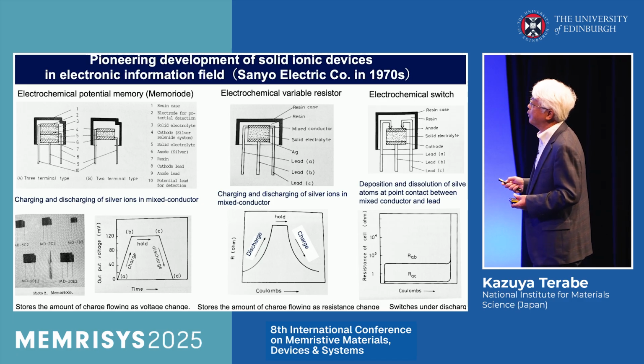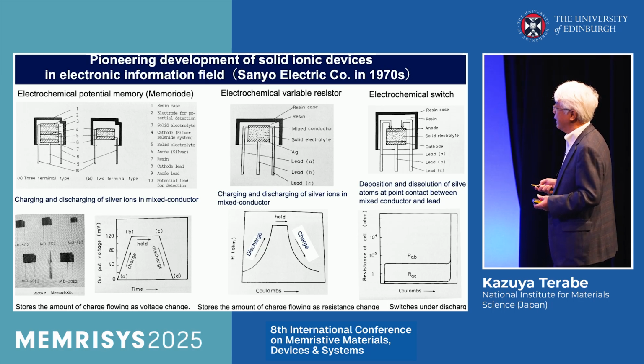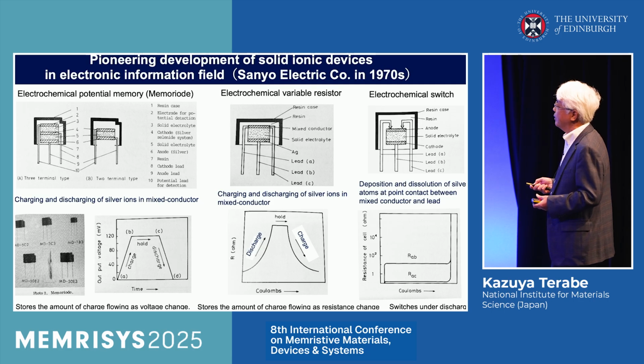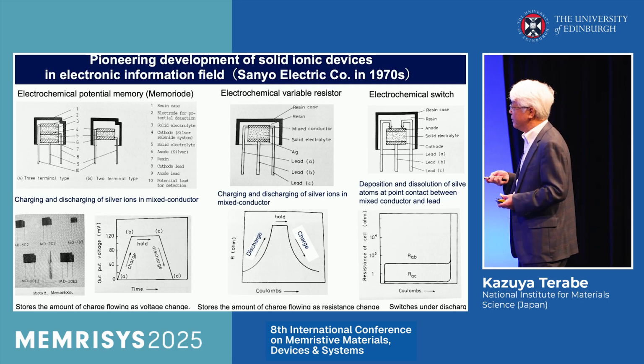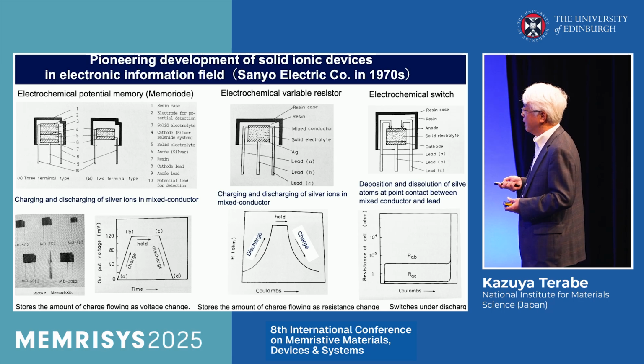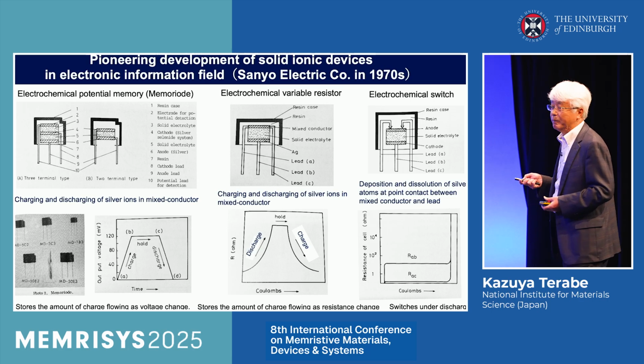This is the electromotive force. This is the actual device, this is time, and this is output voltage. Charging increases the voltage, and it holds, and discharging decreases it like this. So it can store a large amount of charge flow as a voltage change. This behavior is that of a battery.